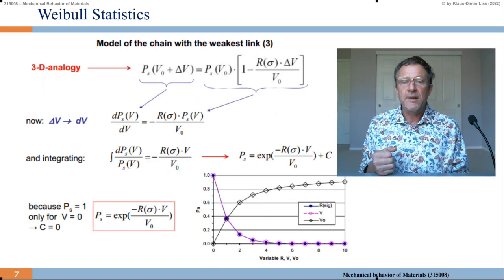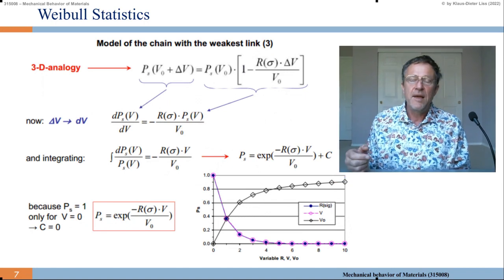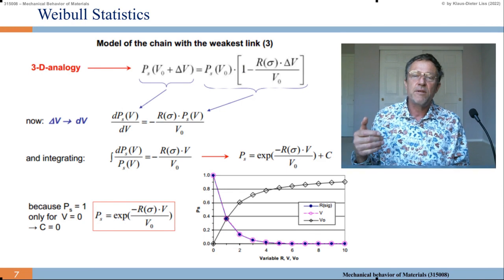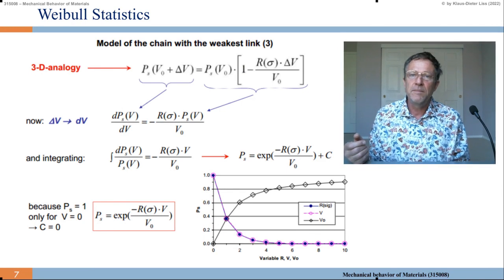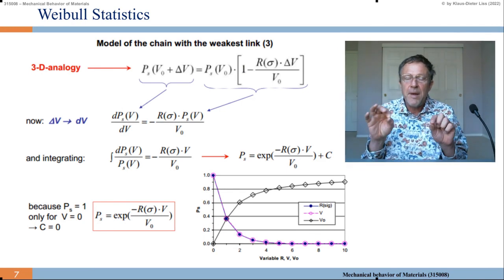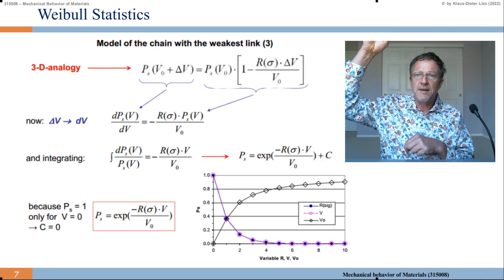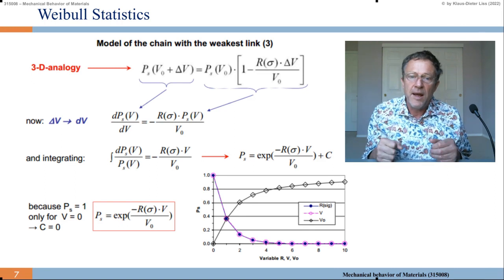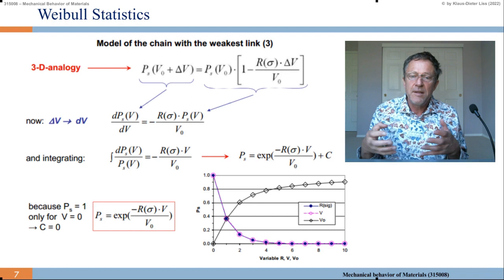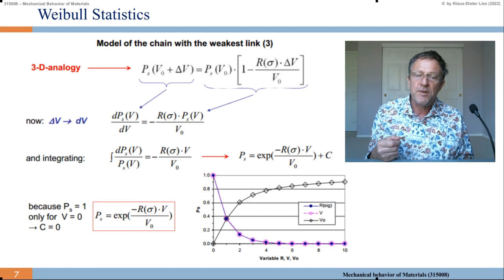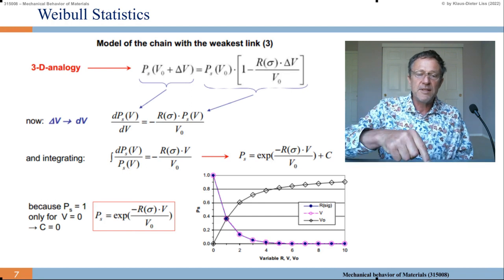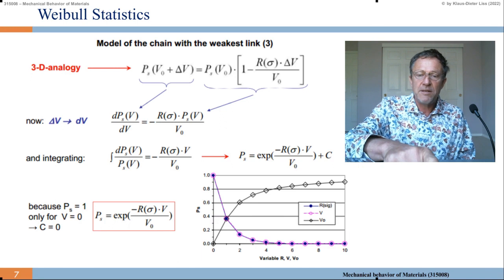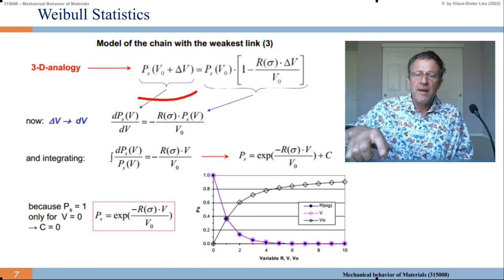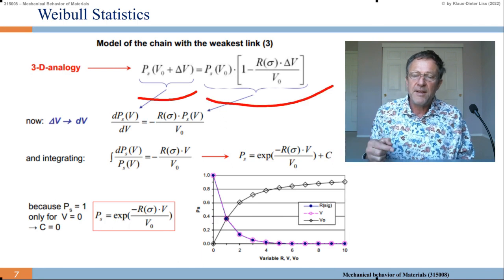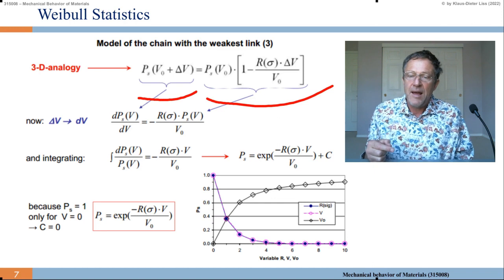We can write down the same thoughts in 3 dimensions, where instead of an L we have a volume. So the failure may occur anywhere in the volume, not just in the linear chain. And if I make the volume bigger, I get the multiplication of the probability which goes with the volume. So we do the same. PS of V0 plus delta V becomes PS of V0 times 1 minus R of sigma delta V over V0.